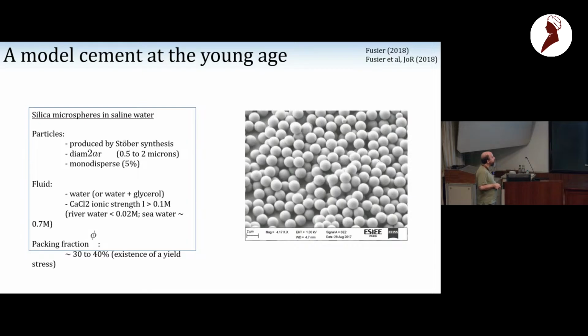So we have here microspheres of silica, and the silica is produced by the Stober synthesis. It's extremely highly controlled. So we have very highly monodispersed spheres of silica, and they are in a fluid which can be water or glycerol, and what's important is that they are ions. It's an ionic suspension. And the typical packing fractions are 30 to 40%.